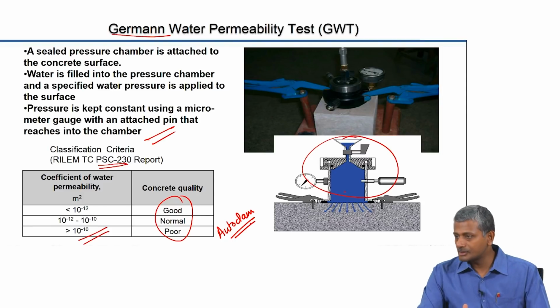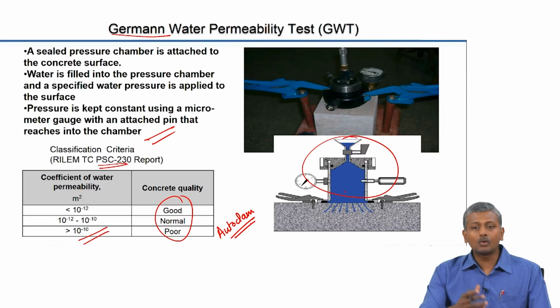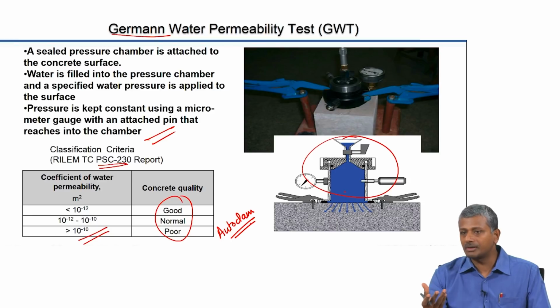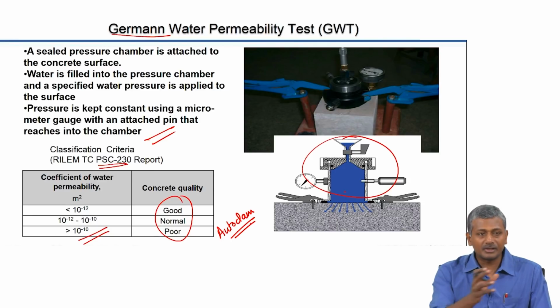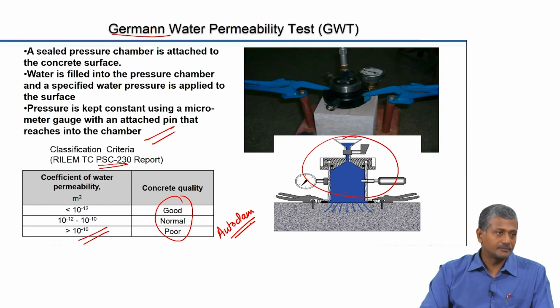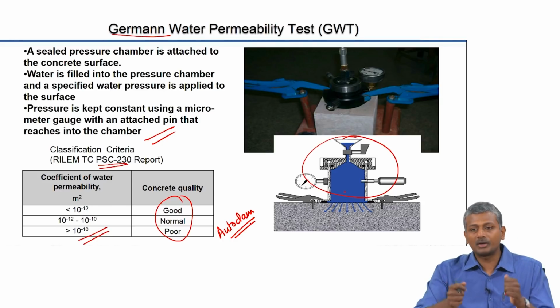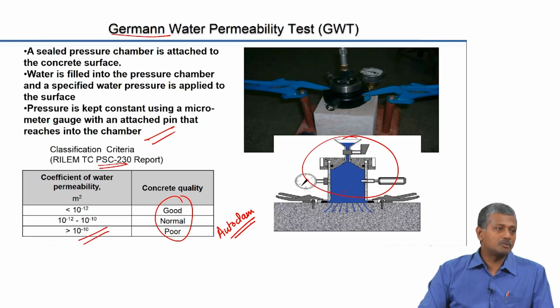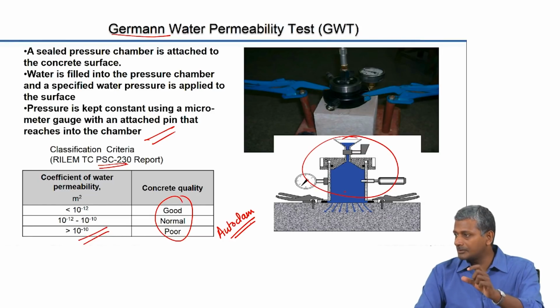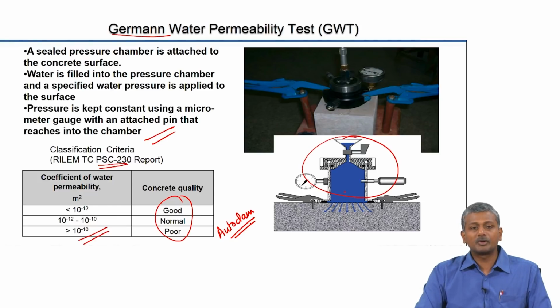Now, the advantage of these non-destructive measures is that now you have a chance to apply these directly on the structural concrete, because the durability test on structural concrete is not really going to damage it unless you remove a specimen to do the test. If you are simply going to be doing it non-destructively, there is no problem at all. So, these kinds of tests can actually be applied for on-site measurement of the quality of concrete. Apart from cover depth, you can also actually directly measure the permeability coefficient.